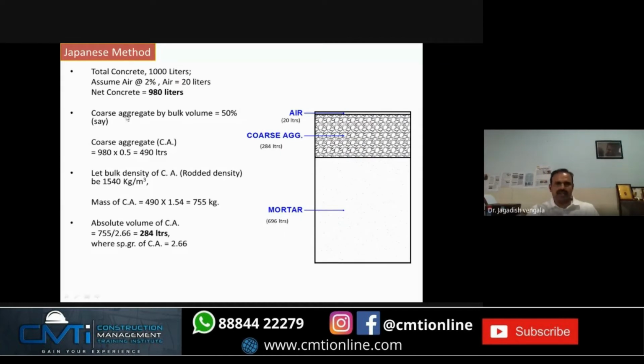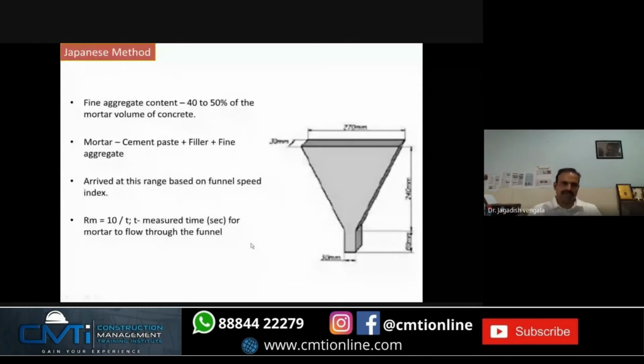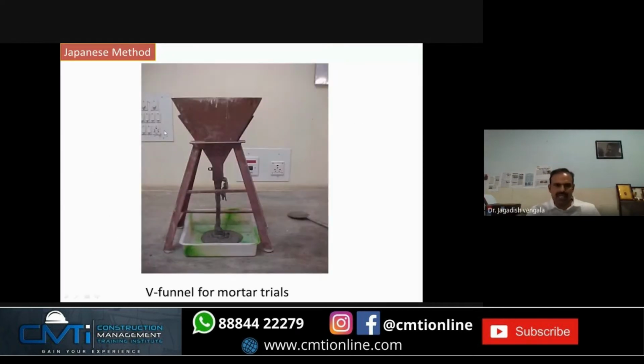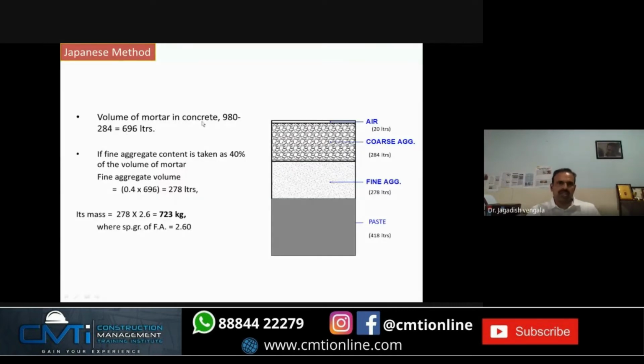So suppose you take 1,000 liters of concrete, assume 2% is air, 20 liters you remove, 980 liters you are designing. Bulk 50%, if you are assuming it as coarse aggregate, 50% of 980 is 490 liters. Then if you multiply with bulk density, you get the mass, and then you can again calculate the absolute volume. And for fine aggregate, using the small V funnel, you actually get the fine aggregate content. So this is the small V funnel. We do mortar trials to get the required mortar quantity. So volume of mortar, if it is 284, then you deduct from 980 and then 40% fine aggregate.